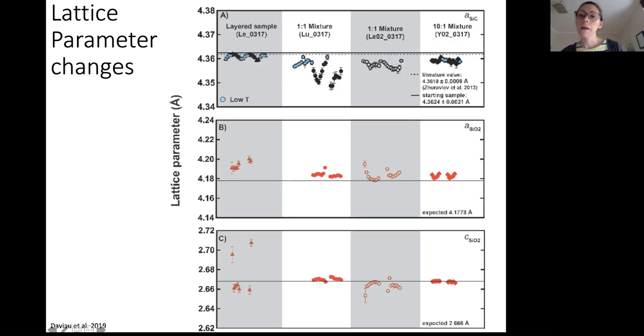A and C. And what we see is that in different samples, this first gray column is the layered sample, there is an oscillation of the silicon carbide zero pressure lattice parameter, which corresponds to where in the quench patterns it got hot and where it stayed cold. These are from maps across the sample. And when you look at these, the silicon carbide is largely smaller than you would expect it to be.